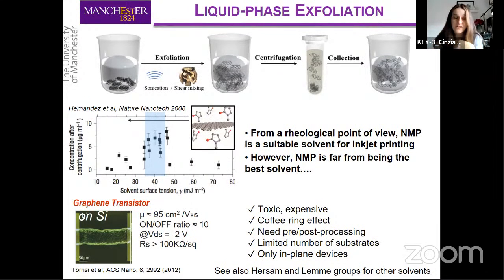On silicon, for example, as you can see from the picture at the bottom, we have a very strong coffee ring effect, and so the substrate will need to be functionalized somehow. NMP is also quite an aggressive solvent, I would say, towards plastic, the plastic of the cartridge, the plastic of the substrate, and so on. So it became quite clear in the community that we needed to make new formulations for inkjet printing beyond the use of standard NMP.